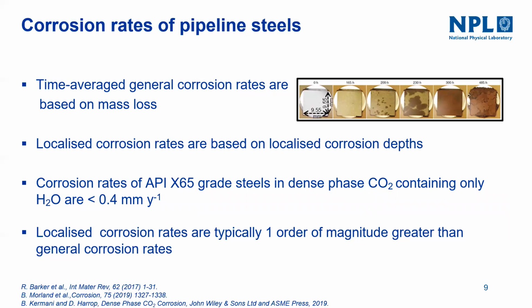And what are the typical values that we are talking about here? For a pipeline steel of X65 grade containing just water, with no other impurities, the measured value is typically less than 0.4 mm per year, and the localized corrosion rates are higher by one order of magnitude. So these are not really acceptable. And with more impurities, the values are significantly higher.